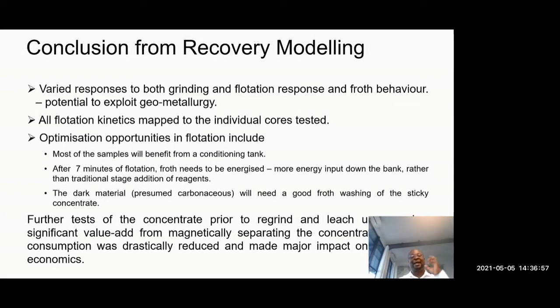So you are really helping the operating cost in a massive way by first grinding without those magnetites and a few other species, and secondly, basically reducing the propensity to chew the cyanide without actually getting any improvement in the gold. So that's what you did. So all this comes from scrutinizing. There are so many opportunities, and of course they are all mineralogy dependent.